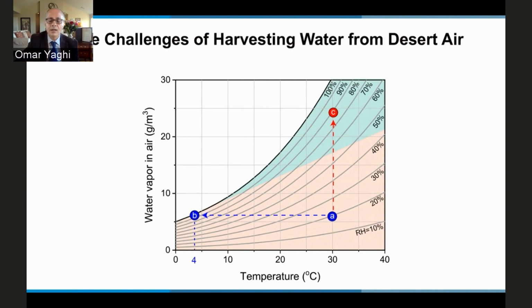But if I have a MOF that can take water out of this air at a relative humidity of 20%, I could concentrate water in that MOF and, in a closed system, create a humidity. And from that humidity, I only need to cool down a few degrees to get the water out. Okay, that's how MOFs work.